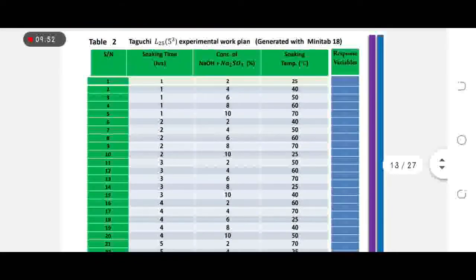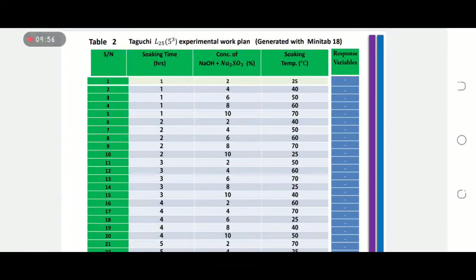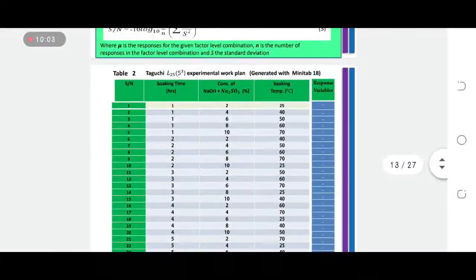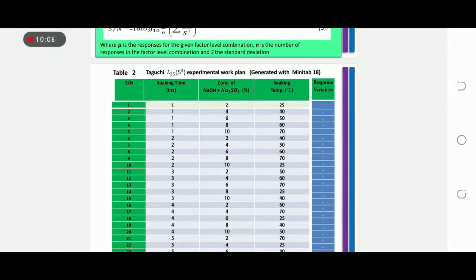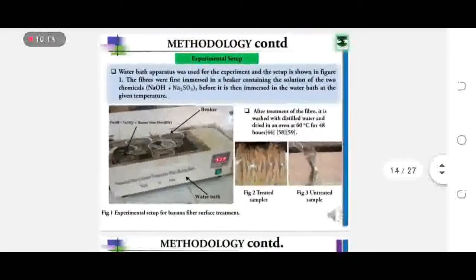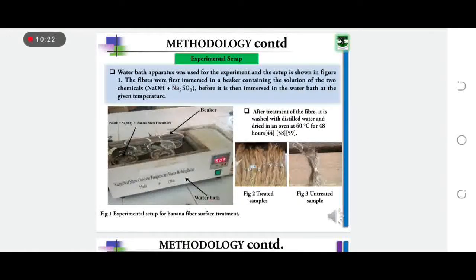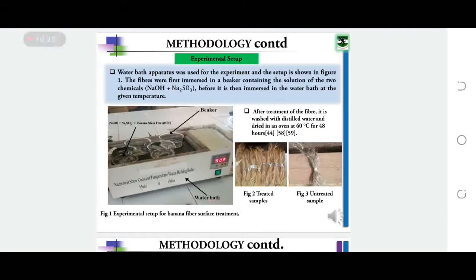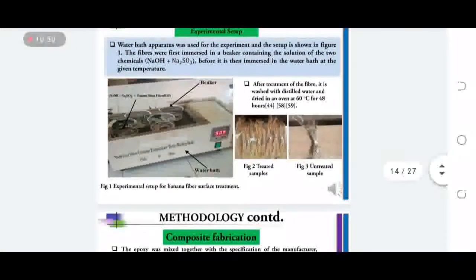So Table 2 shows the Taguchi-generated design. We see that each of the parameters has 5 levels, so we have 25 experimental runs in our Taguchi design. Our experimental setup is shown in Figure 1. What we have here is a beaker, and we insert our banana fiber inside the beaker, which is then dipped into a water bath and covered. It's left open in the diagram just for emphasis. Then we put the regulator at the particular temperature to regulate the temperature at which we are treating. Figure 2 is the treated sample, while Figure 3 is the untreated sample.